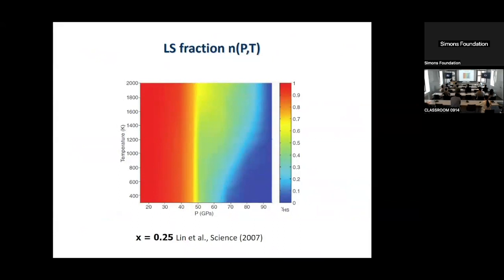It's not major, but we're not trying to get melting temperatures of iron here at above 150 GPa. This is still lower mantle, lower than 135 GPa. It doesn't make much difference, but at higher pressures you have to care about that, and it makes a difference. It affects the melting temperature considerably, 800 Kelvin, deep in the core.